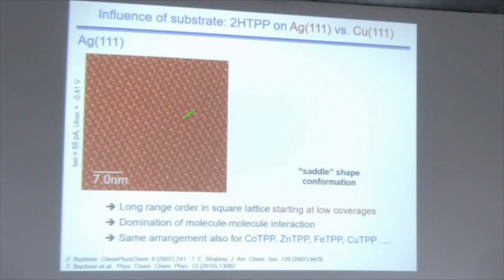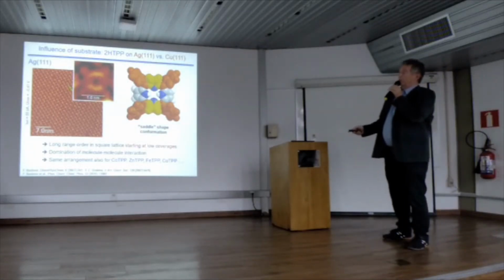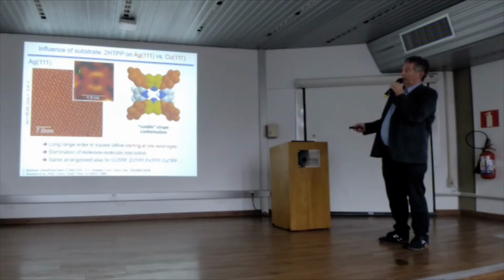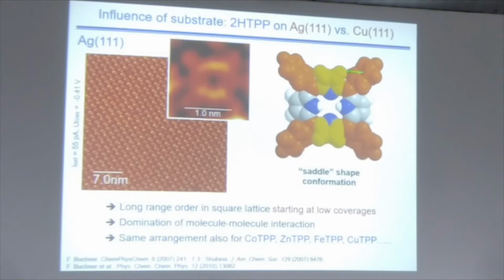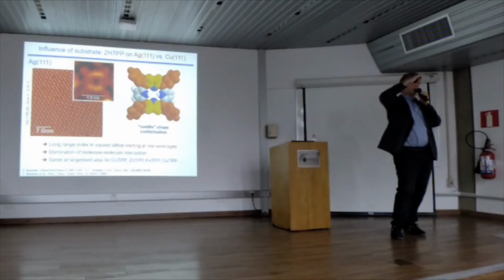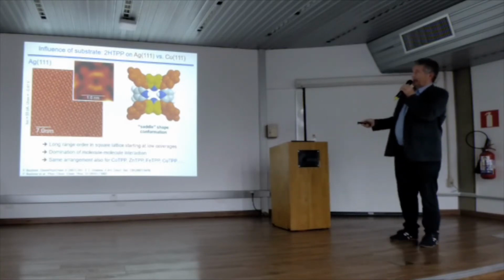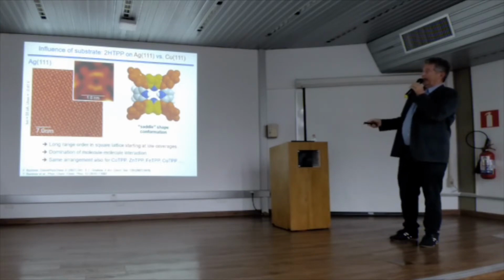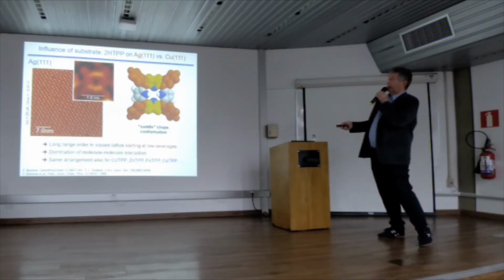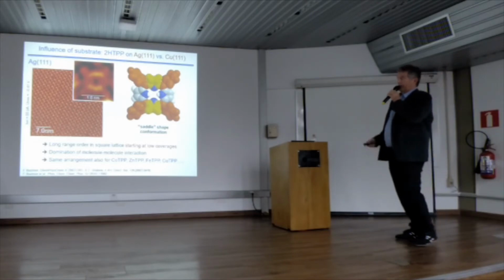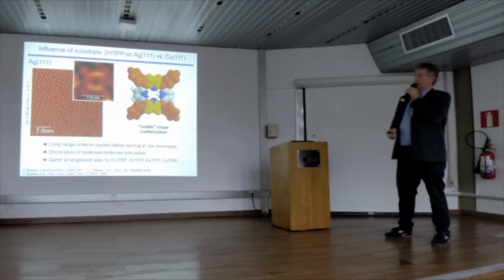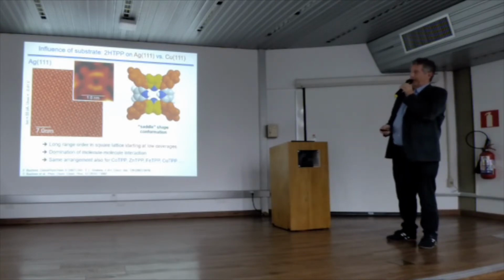Of course, you can look in a little more detail at these molecules, and with this better resolution you see this molecule here. Here you have 4 side groups, these are the 1, 2, 3, 4 side groups. And what you also see is that the molecule doesn't have a 4-fold symmetry, but a 2-fold symmetry, and this comes about because the molecule wants to get as close as possible to the surface. The phenyl groups could stand upwards, then you have a large distance, but if they tilt down as much as possible, until the hydrogens here have steric repulsion, you get it closer to the surface. This leads to a saddle-shaped deformation, with 2 pyrrole groups looking towards us and 2 looking towards the board. So that is a relatively simple system, and it took us a while to get used to that, but then it is pretty easy. Then we move on to copper.